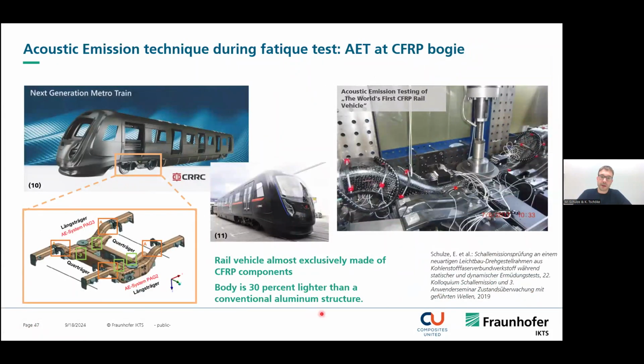So whatever is needed, we can only integrate the transducers, but also electronics, however it is needed for our application. Last example, back to the acoustic emission. Really nice, colorful slides in the end. This was an example of an acoustic emission measurement campaign during the design and manufacturing of a CFRP bogie in a railway. This bogie was totally manufactured of carbon fiber, and we measured with acoustic emission sensors. Here on the right side, you can see the small acoustic emission sensors. The acoustical events coming during tensile tests, during bending tests of the bogie.